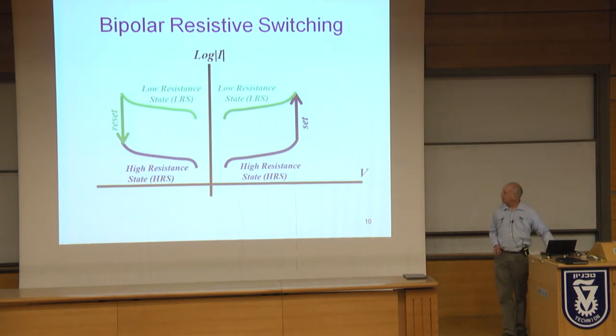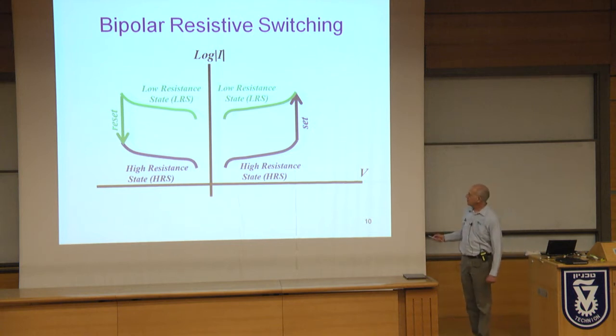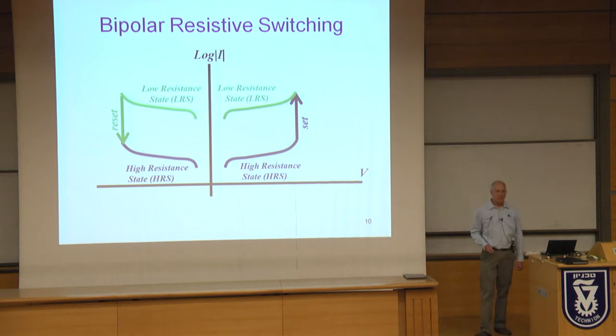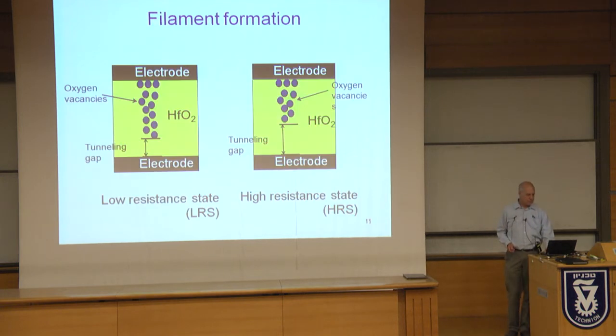That's a typical resistive switching IV curve. We can see first that there was a high resistance state, HRS, then a set operation brings the material into the low resistance state, and going backwards to the negative voltage, we are switching by a reset operation to the high resistance state again. This is called bipolar resistive switching. There's also unipolar resistive switching where everything is done at the same polarity.